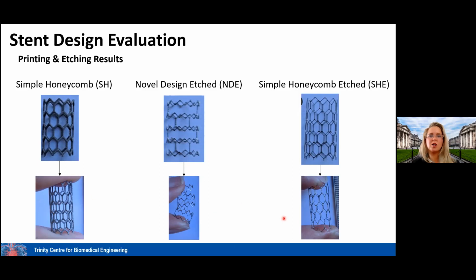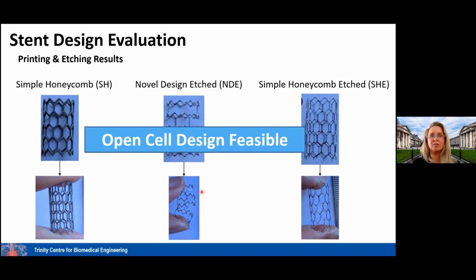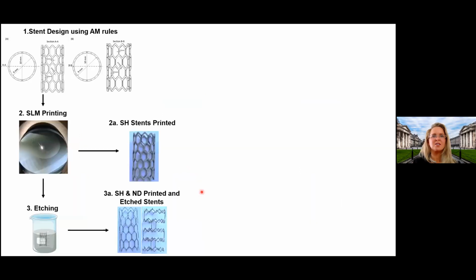Whereas with these two geometries, even when we thin the struts, it doesn't give us that conformability because we have closed cells, all connected, which gives that real rigidity across the stent. So it's only in opening up the cells that we can get that flexibility. So it is feasible, once we etch, to get these open cell structures and keep the additive rules. We were quite happy that we could enable this flexibility in design.